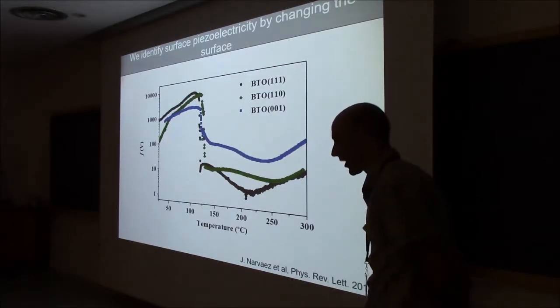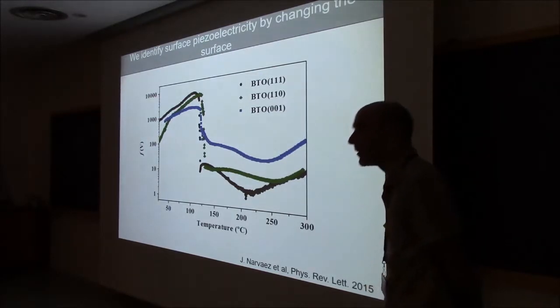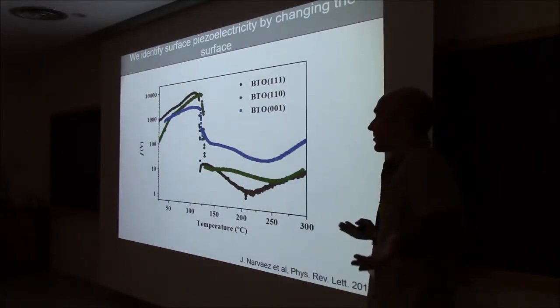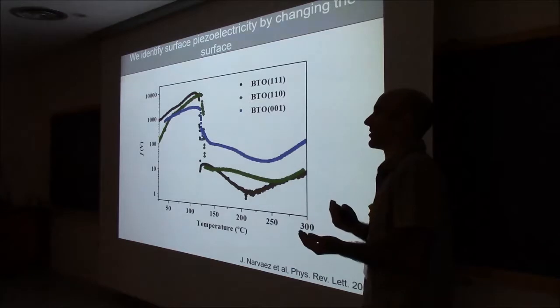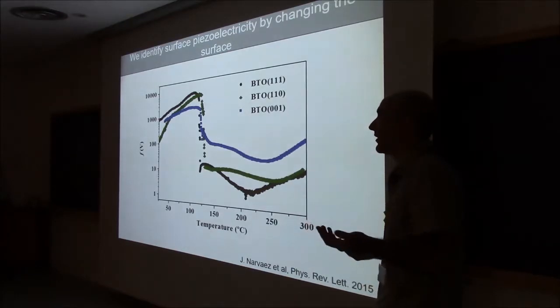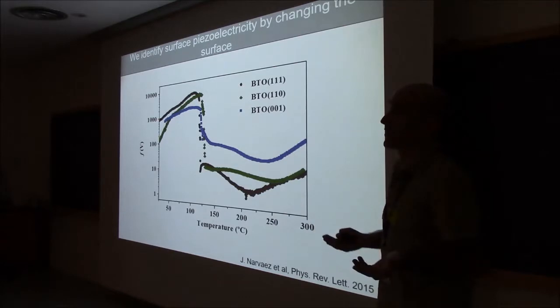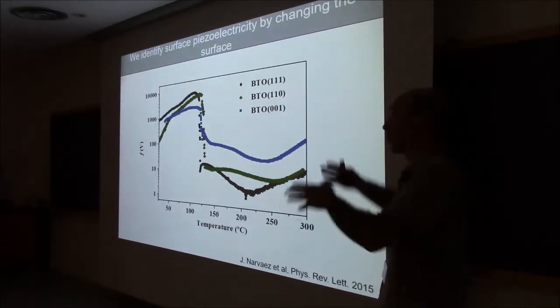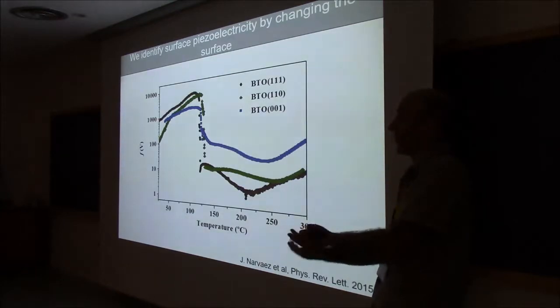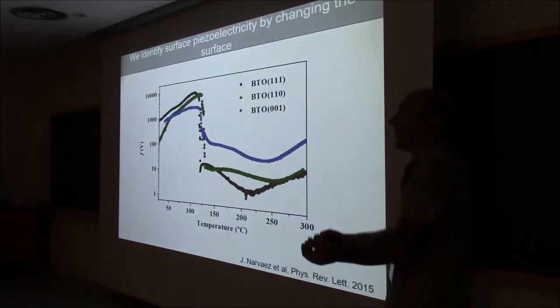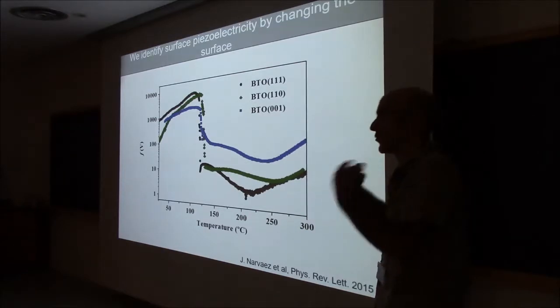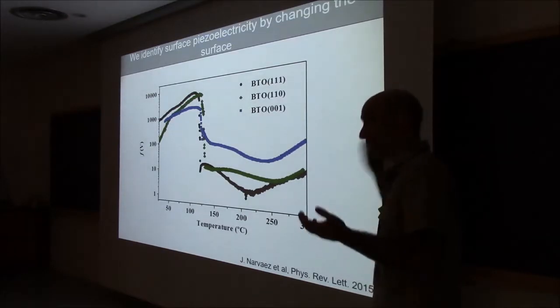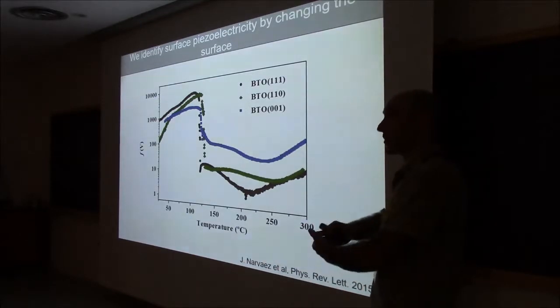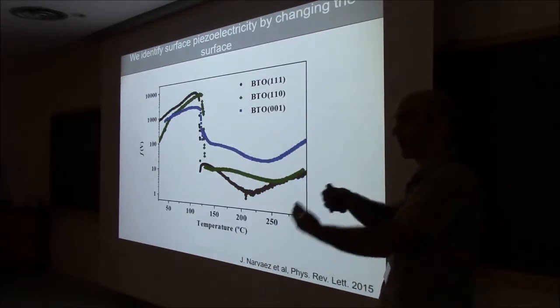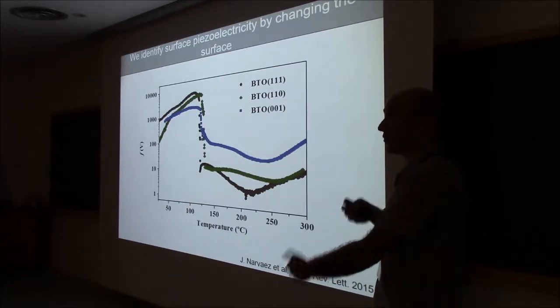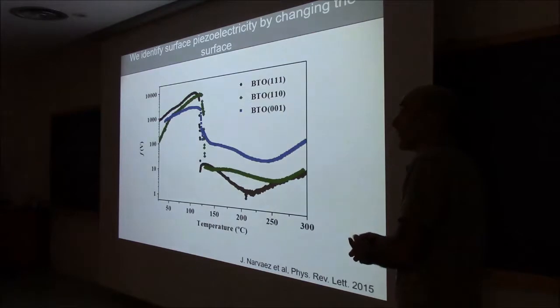That's a complicated question. As you try to bend it, it will try to change its polarization because it's piezoelectric. How much it manages to switch polarization will depend on how efficiently you can screen that polarization. If you cannot screen it at all, because there's not enough adsorbates in the atmosphere or your dielectric crystal has a very low dielectric constant, then this surface piezoelectricity will be almost negligible. But if you have a lot of adsorbents that can go in and screen this polarization, then the polarization will develop. Now, whether you can measure it or not is different. But the better you can screen, so the more adsorbents you have, in theory, the bigger the surface piezoelectricity that you can achieve.